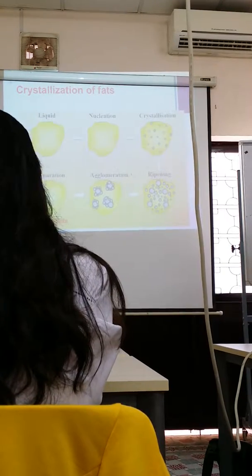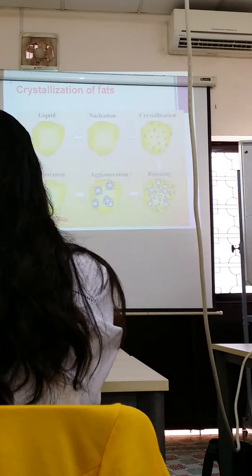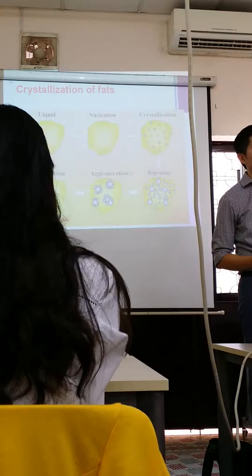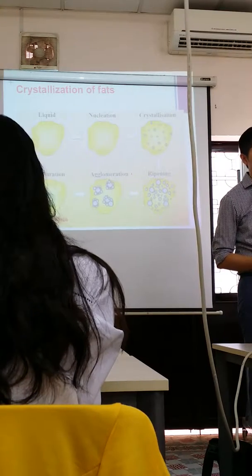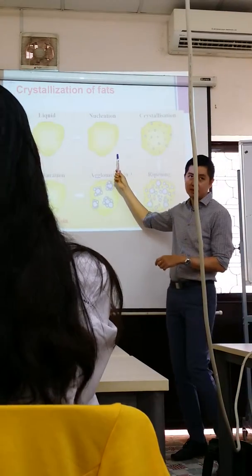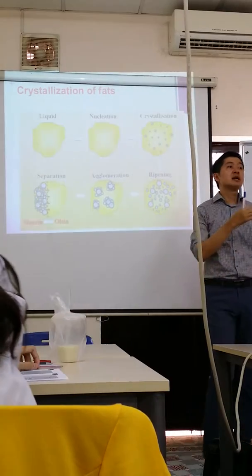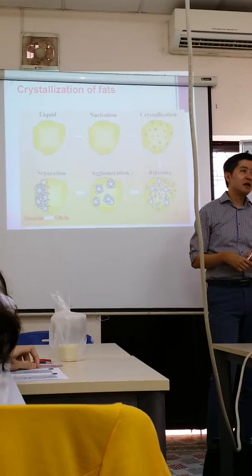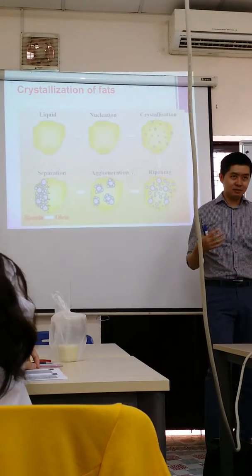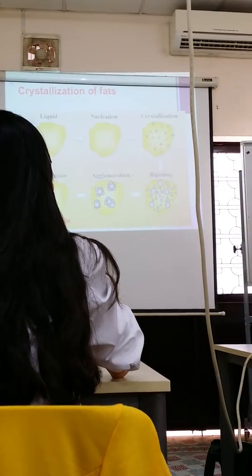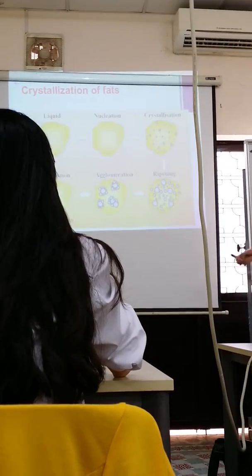Because sometimes when different harvesting period, different geographical region, the oil may have different percentage of DAG and MAG. Even slight difference, 0.1% different, 0.5% different, it will have great effect on this. Because crystallization process is a cooling process. Cooling process is also very energy intensive, need to consume energy. Okay, so companies do not like to spend a long time for crystallization.